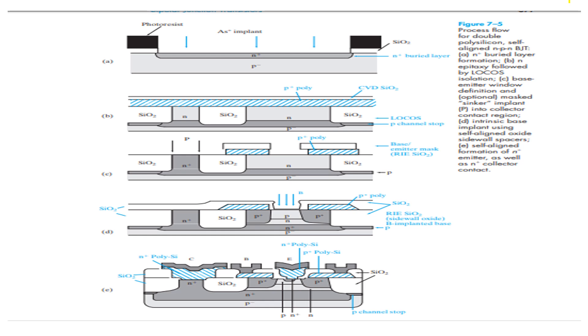A heavily doped extrinsic base is formed by diffusion of boron from doped polysilicon layer into the substrate in order to provide a low-resistance, high-speed base ohmic contact. An oxide layer is then deposited by a low-pressure chemical vapor deposition which has the effect of closing up the base window that was etched previously and boron was implanted in the window. This base implant forms a more lightly P-doped intrinsic base through which most of current flows from emitter to collector and this is shown in figure 7.5D.